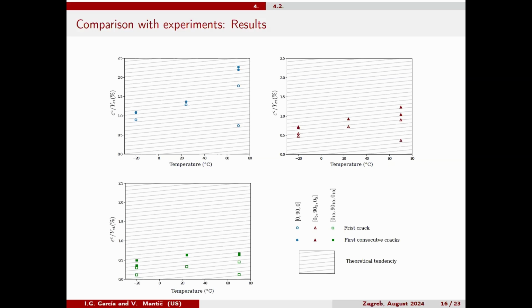And in green, you can see these lines correspond to the tendency predicted by the theory that we are presenting here. As you remember, this is linear with the temperature, and that's why here you have a straight line. We are plotting a line without focusing on one of the 4 theories that we are trying to improve, because otherwise we would have one for each theory. We want to do this comparison independent of the theory, Bourgeois, incremental, coupled, etc., because it would introduce in our comparison all the fracture and strain properties of the lamina, etc. So in this case, all the results depend only on the elastic and thermal properties that, as you know, are much easier to obtain, and they are more reliable.